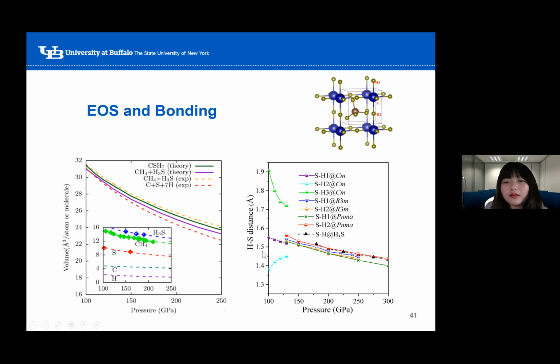We also studied the S-H bonding by plotting the H-S distance as a function of pressure for several phases. Using the R3m as an example, under pressure, SH1 and SH2 bonds are approaching each other, and SH3 bonds are decreasing as the phase undergoes the pressure-induced bond equalization. However, due to the fact that the intercalation of methane molecules would break the symmetry, the SH1 and SH2 bonds are slightly different, and both of them are slightly shorter than the SH bond in the trihydrogen sulfide.